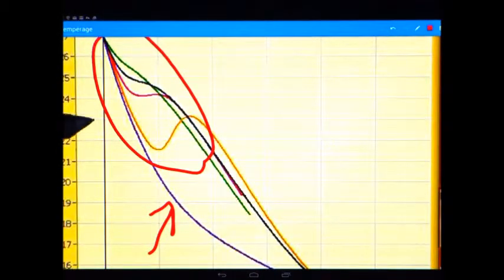Remark about the plateau. Some users used to believe that we must reach a plateau for a good temper, and this was an information given by the manufacturer a long time ago. It's not correct at all, although it works in maybe 50% or more of the situations. The slope of the curve should be correlated with all manufacturing conditions, and as we have said earlier, especially with the cooling rate.